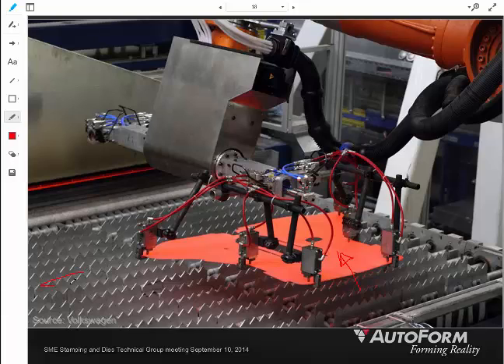The furnace would have been back to the left of this illustration, and the press and the die are probably going, oh no, here's the furnace, excuse me, drawing it sideways. There's the furnace, right? So the material came out this way out of the furnace. Here it is getting picked up after coming out of the furnace, and it's going to go this way into the stamping operation. All right, that is red hot, and that material at that temperature is above the recrystallization temperature